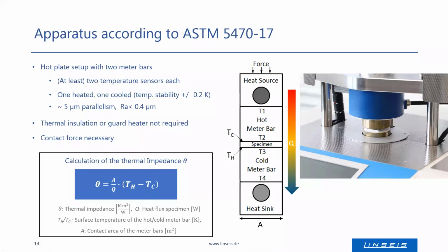The temperature in the meter bars is then measured by some thermocouples mounted at known distance. Here 4 thermocouples are placed which measure the temperature, and those thermocouples have a known distance to each other, and by that one can determine the heat flux.